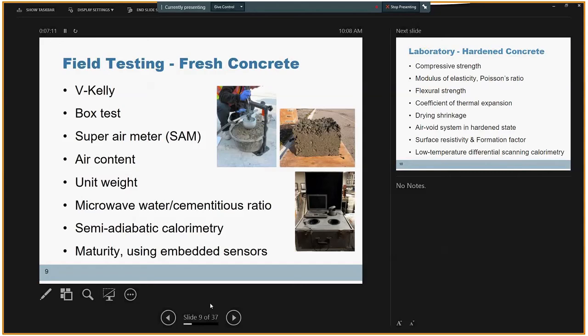So for the fresh concrete properties, the field testing we had focused on workability of the concrete, air void system of the concrete, water cement ratio of the material using the microwave test, and investigating the kinetics of hydration using semi-adiabatic calorimetry, and also monitoring the maturity of the concrete mixtures.